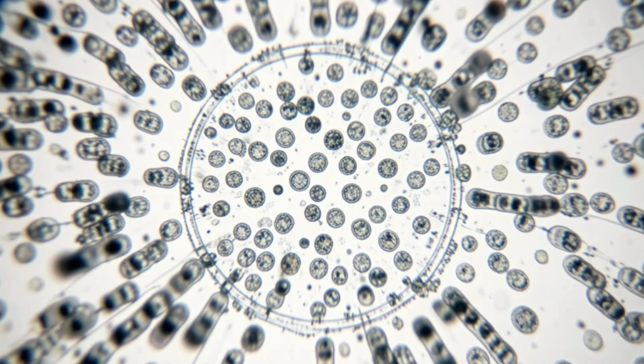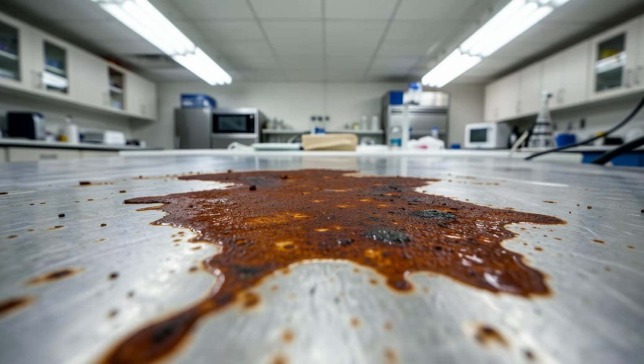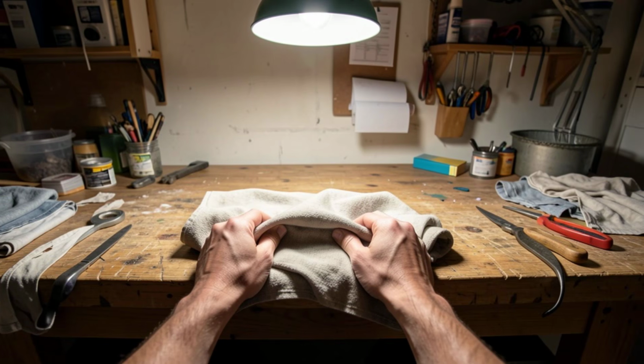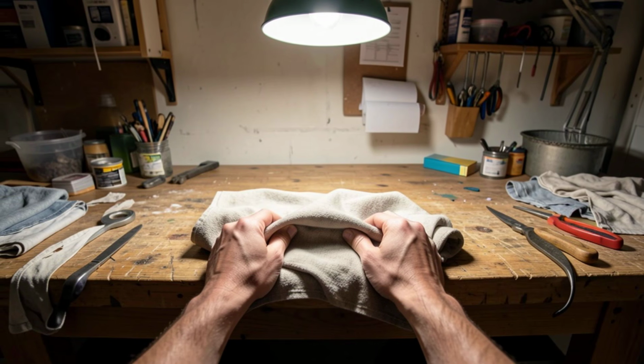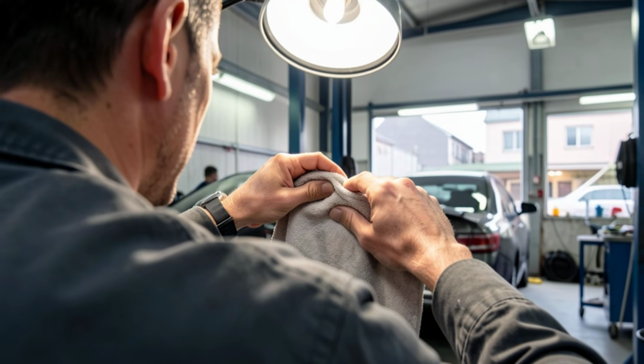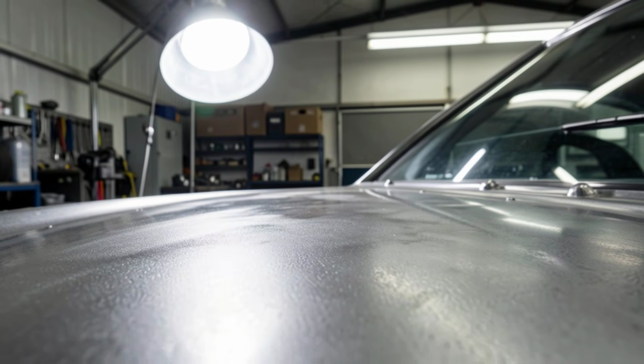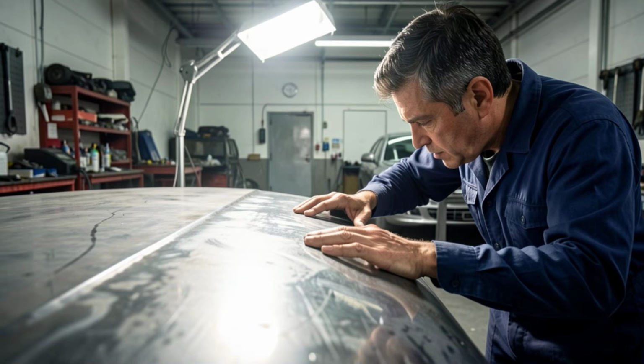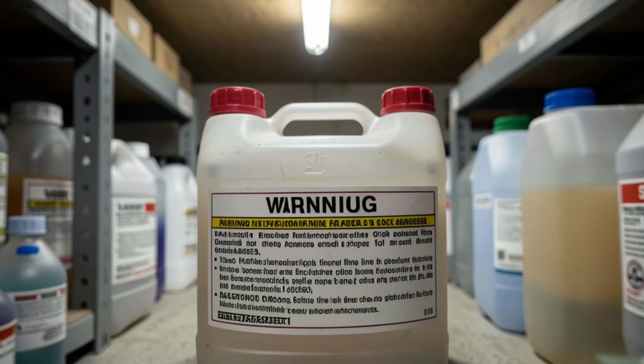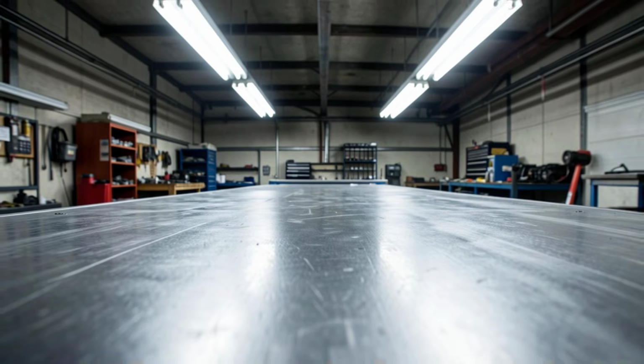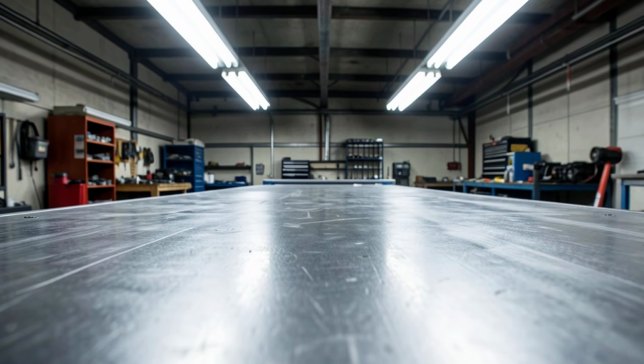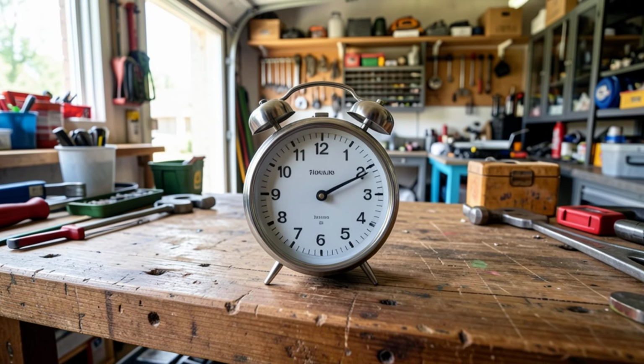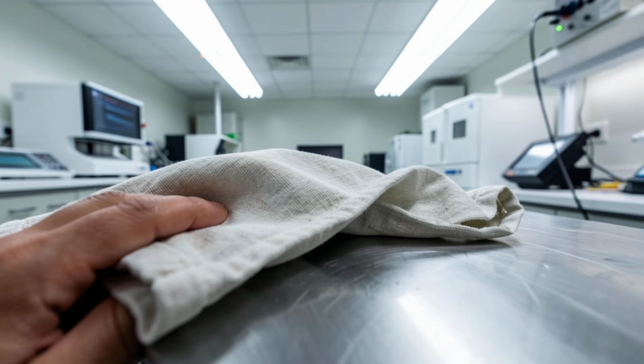Leave it in place for exactly 15 minutes. Do not go to 20 minutes. Do not go to 30 minutes thinking that more contact time means more rust removal, because the chloride ion activity at the base metal surface becomes increasingly aggressive after the iron oxide is fully dissolved, and you do not want prolonged chloride contact on freshly exposed bare steel. Set a timer for 15 minutes. When the timer goes off, remove the cloth.